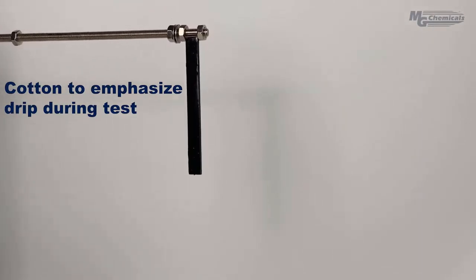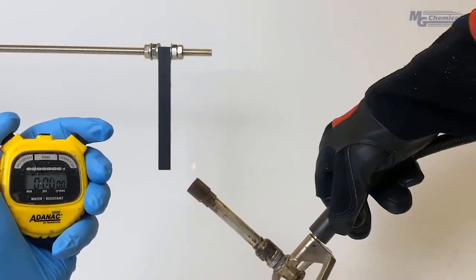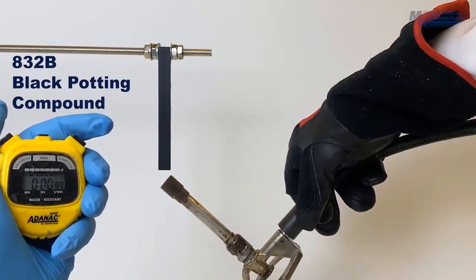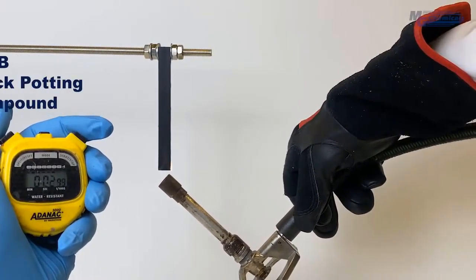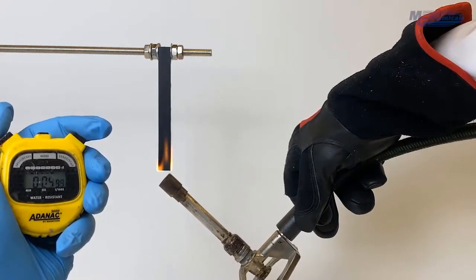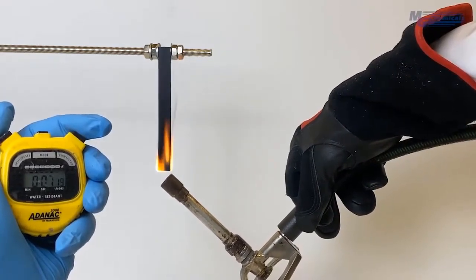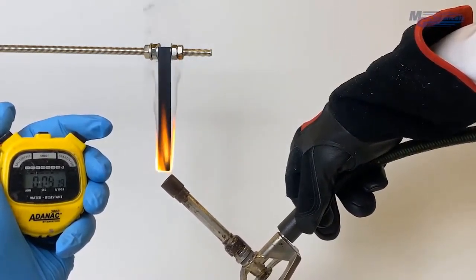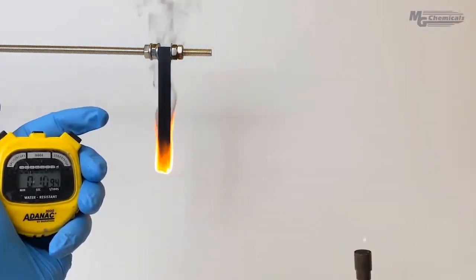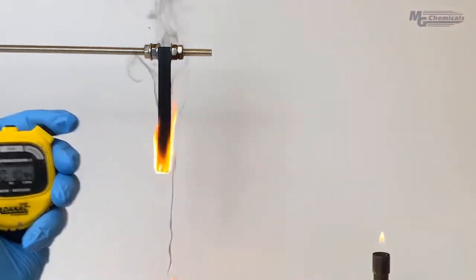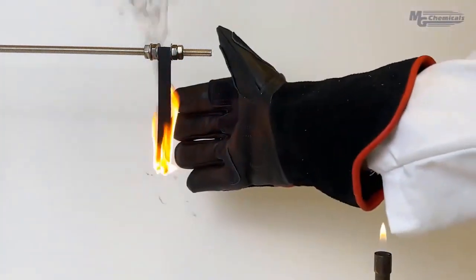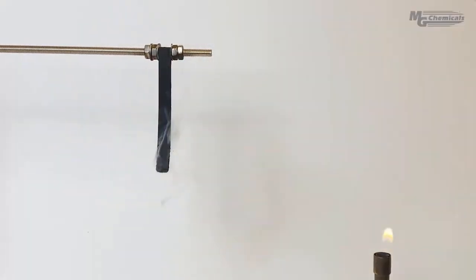Cotton balls are placed at the base of the apparatus as a way to detect whether particles from the sample drip. In our first example, let's look at what happens to 832B, a general-purpose epoxy, when we run it through the test. In step 1, we hold the flame to the sample for 10 seconds and then remove, waiting for the flame to extinguish. Here, we quickly see the flame spread through the sample, reaching an uncontrollable burn. This would be considered a fail.